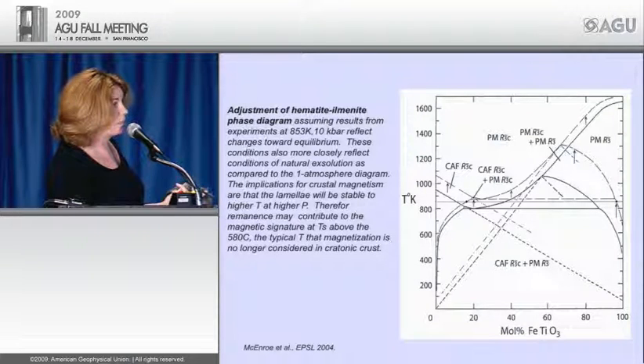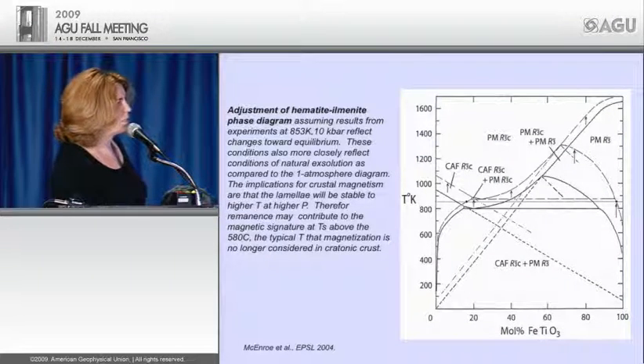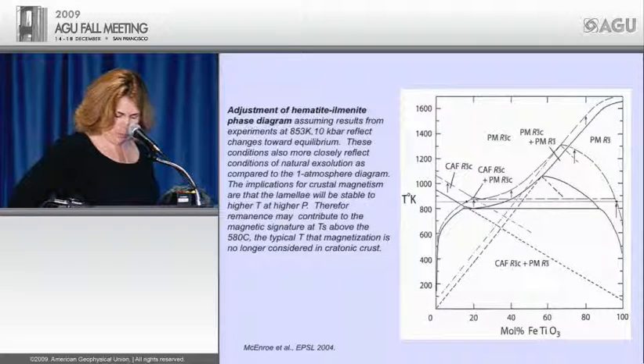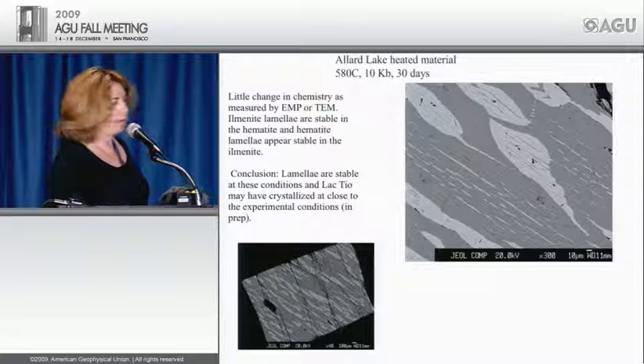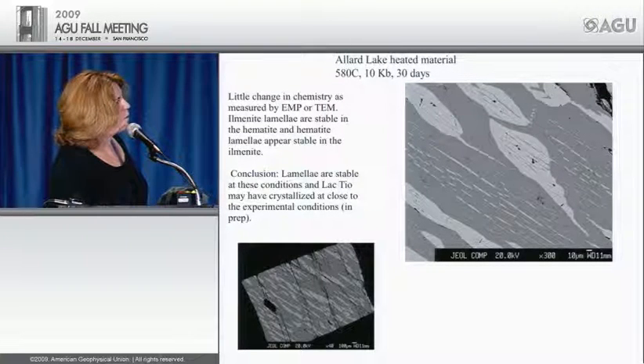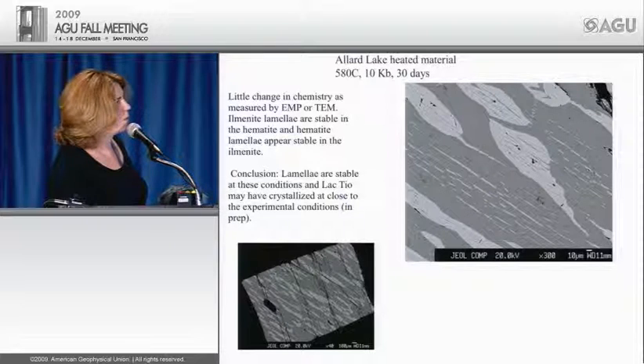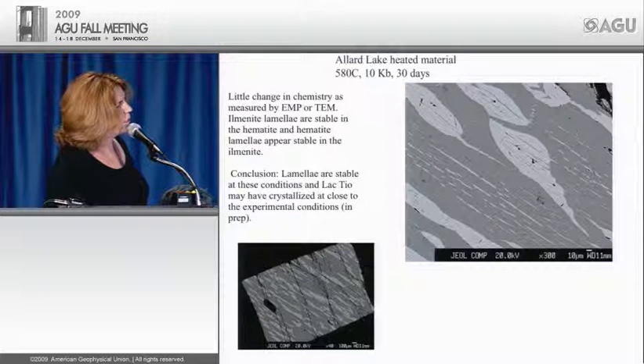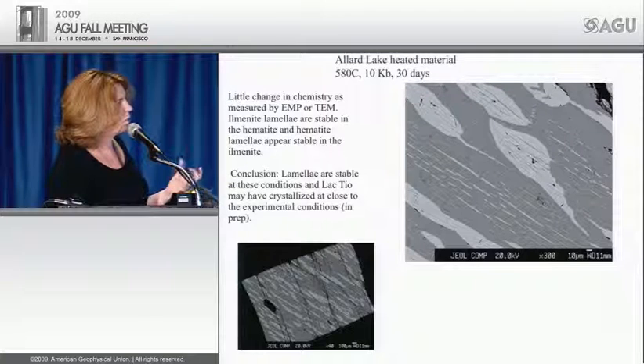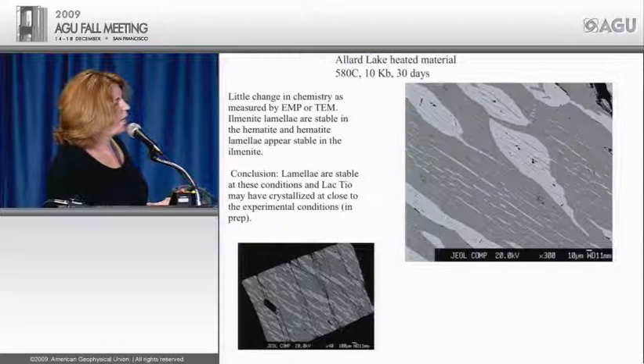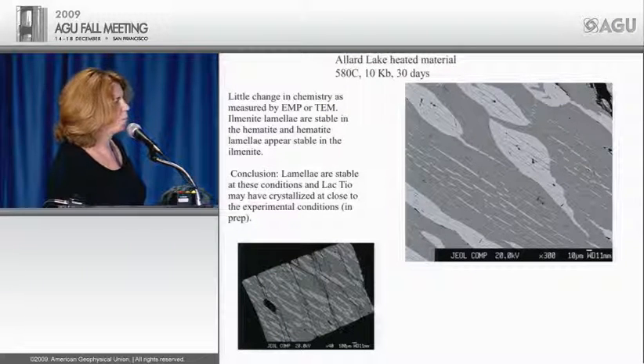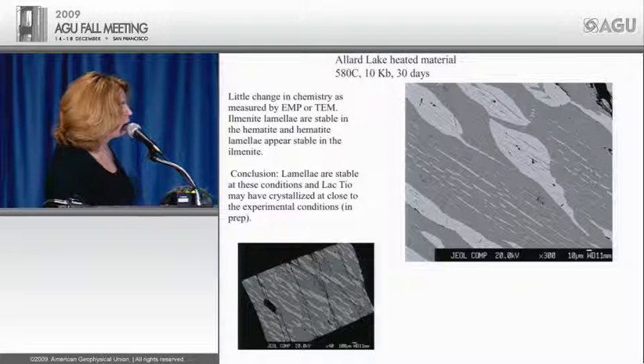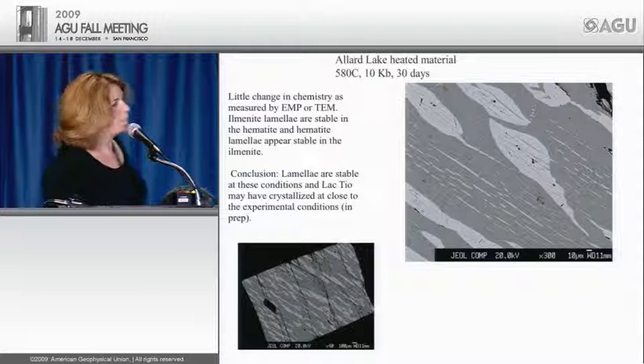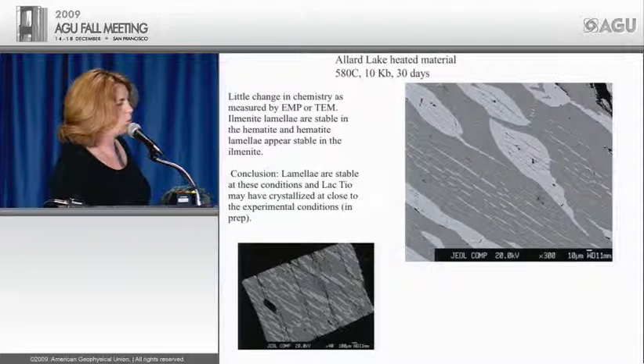And therefore, we have to consider the fact that these lamellae are there and that they will contribute to the magnetization. And then, of course, if one thinks about this further, when we were looking at the Swedish granulites or other rocks, what we found was that the lamellae were very coarse. I was dissatisfied with the fact that I didn't feel we had really answered the question about the difference between what was happening in the hematite lamellae with the ilmenite and what was happening in the ilmenite with the hematite lamellae. And so I used an Allard Lake sample because here the initial lamellae, some of them are very coarse. And in this way, we could be looking at a hematite host as well as an ilmenite host in the same experiment. Now, what happened after 30 days, 10 kilobars, and at 580 degrees wasn't very satisfactory. Nothing really happened. I mean, the TEM chemistry shows that there was hardly any change.